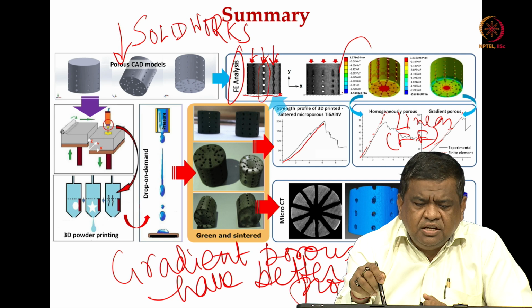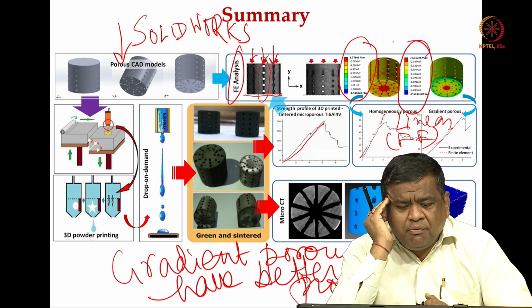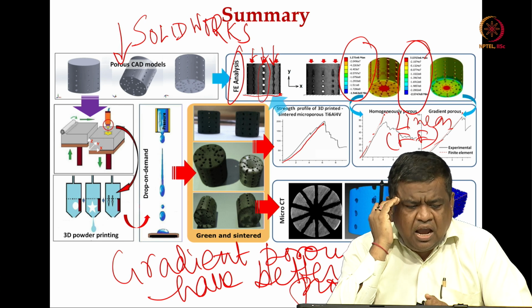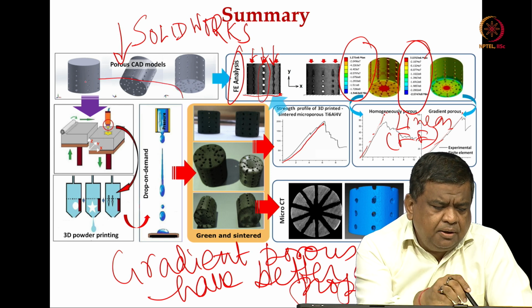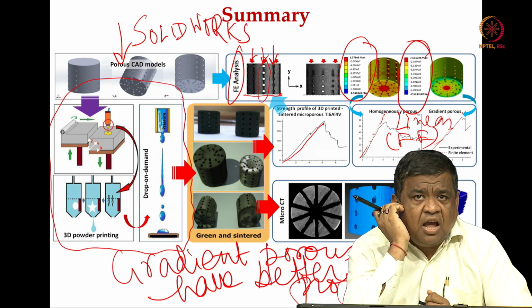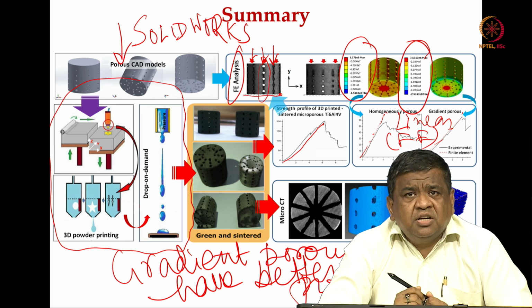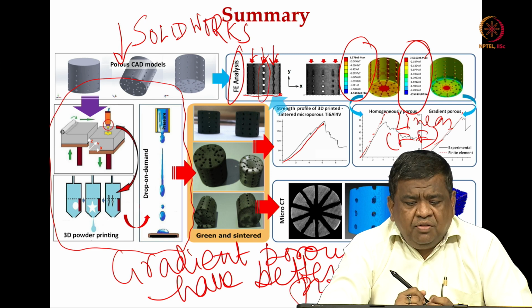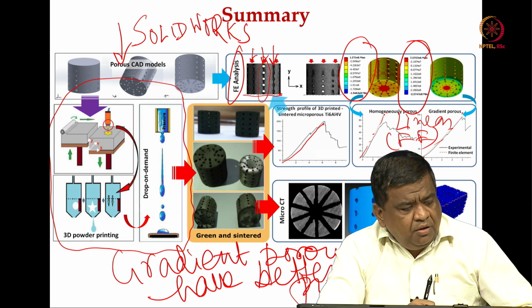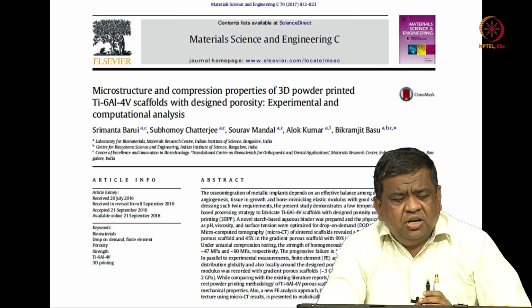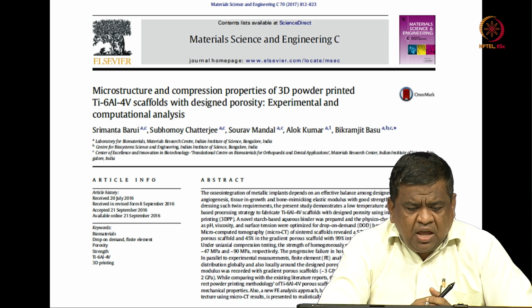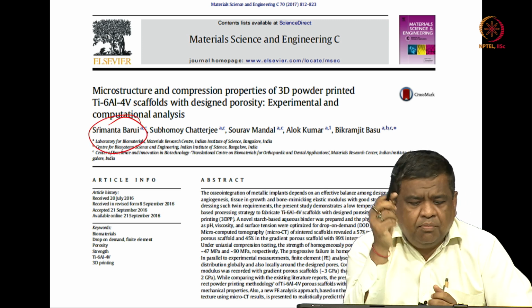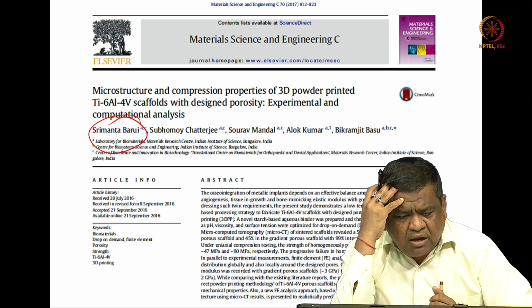We have also seen how the stress concentration, particularly sigma YY, varies in both homogeneously porous and gradiently porous materials, and these materials were essentially printed using a starch based binder like maltodextrin added to deionized water. Therefore, surface tension is much lower than that of deionized water, and viscosity is also within the printable binder range. This scientific case study was published a few years ago, and the lead author was Srimanta Barui, who is currently a postdoc in the United States, and it is 3D powder printed Ti6Al4V scaffolds with designed porosity.